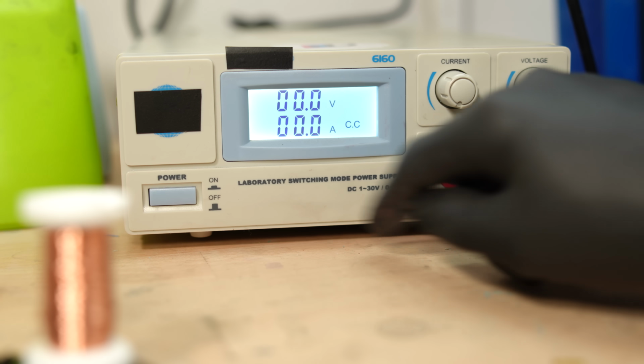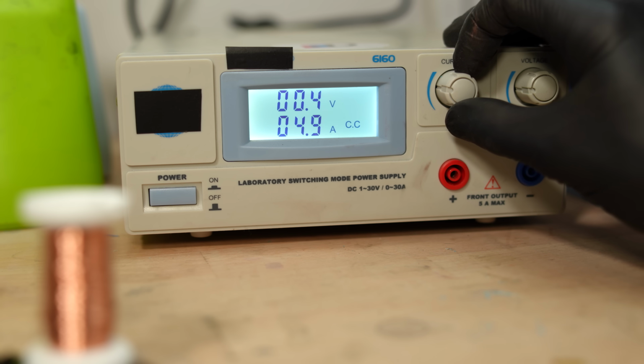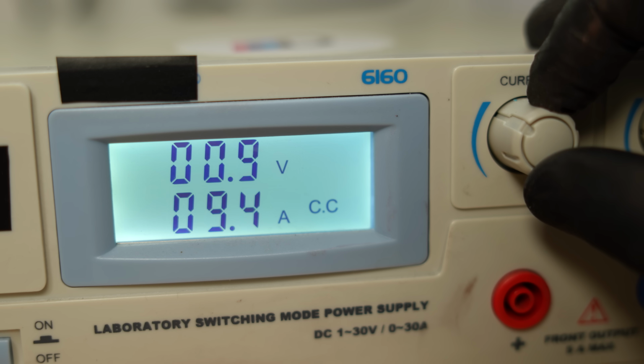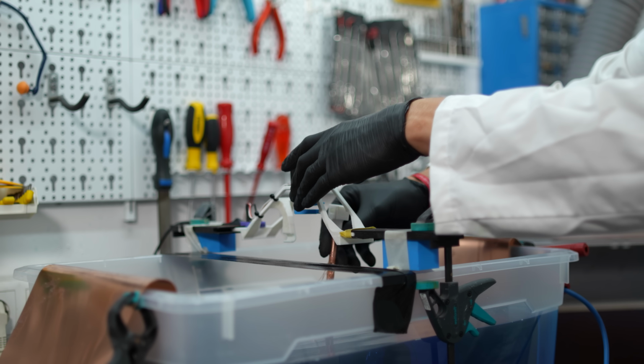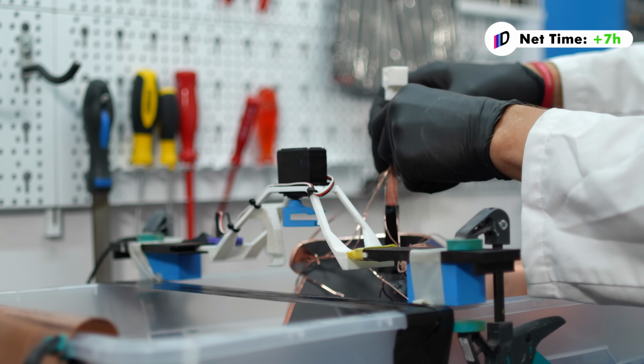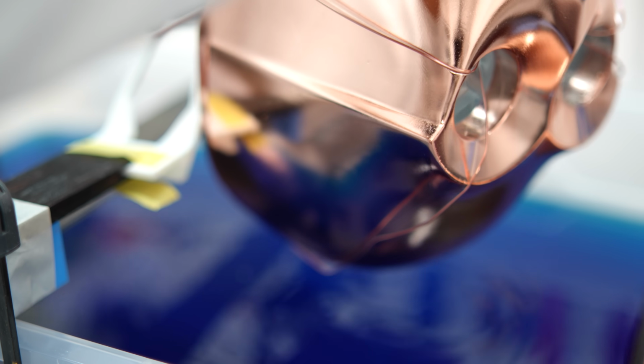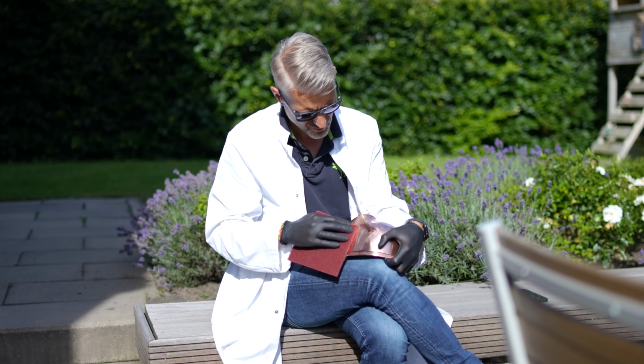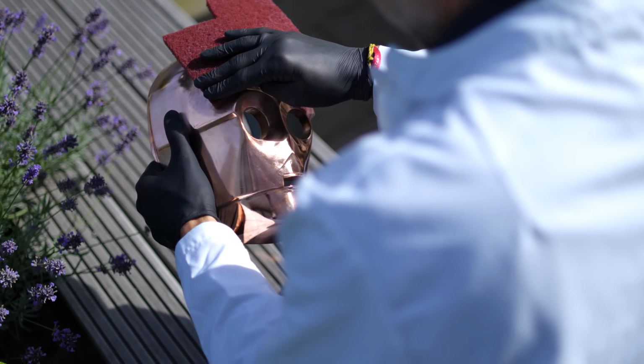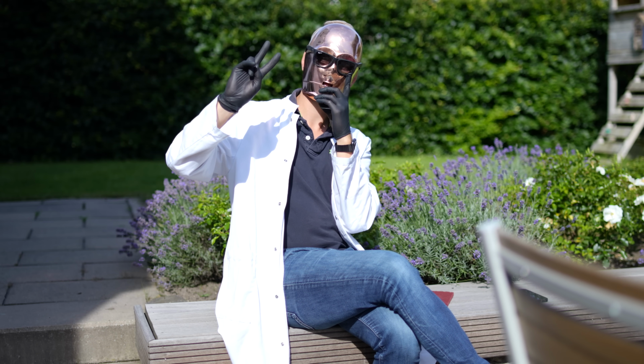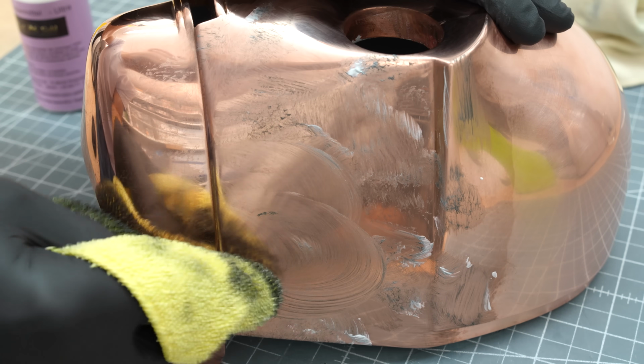I set the power supply to constant current and then I let the electrochemistry work its magic for 4 hours. If everything went well, we now have a 3D print coated with about 0.2 mm of copper. Now begins the long process of polishing. To achieve a mirror finish, I go through various sanding and polishing compounds.